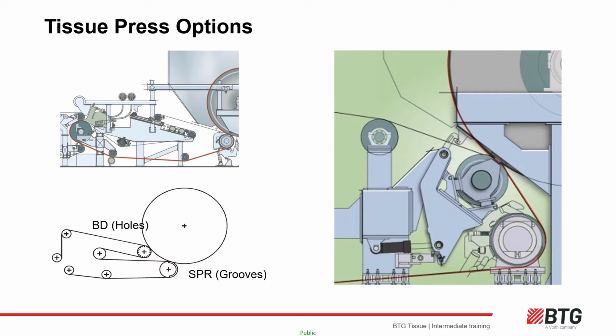Some newer machines have an extended nip or shoe press. The shoe press extends the length of the nip. Prior to the shoe press we will have a suction dewatering roll. A lower shoe press load gives lower post-pressure roll consistency, meaning a wetter sheet at the nip. This leads to highest bulk, softness and maximum fibre savings. A higher shoe press load gives higher post-pressure roll consistency, meaning a drier sheet at the nip. This leads to highest hand feel in terms of smoothness and highest energy efficiency but lower bulk.